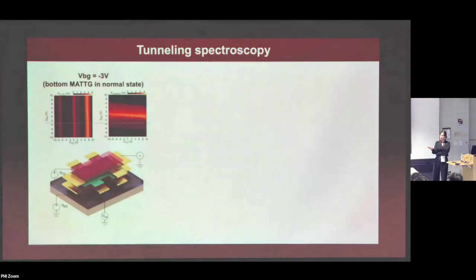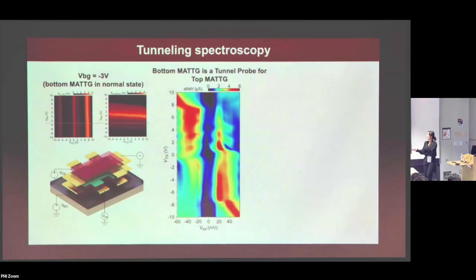So now we can get into the actual business of tunneling. In order to do tunneling spectroscopy, what we do is park our gate voltage for the bottom layer to be in some normal state. And using that bottom magic angle twisted trilayer graphene in a normal state, we're going to probe and study the top magic angle twisted trilayer graphene. So here is the tunneling conductance map as a function of the top gate voltage, which controls the doping of the top magic angle twisted trilayer graphene.